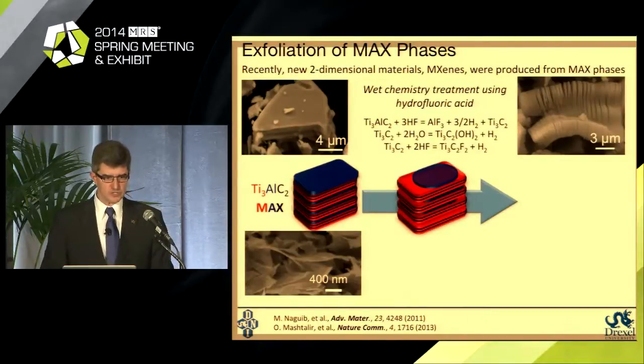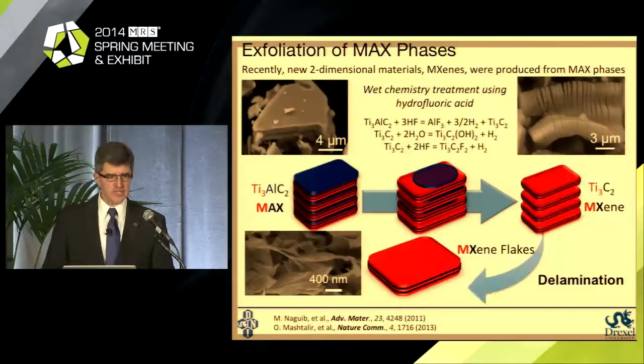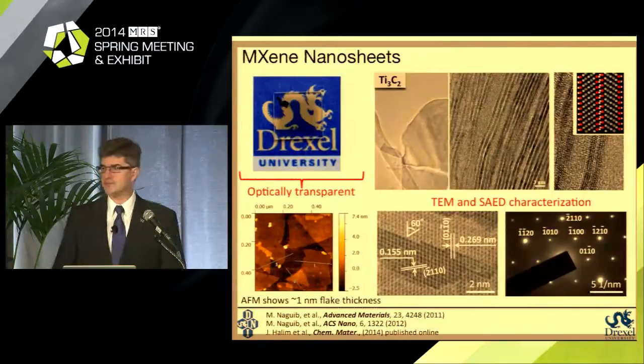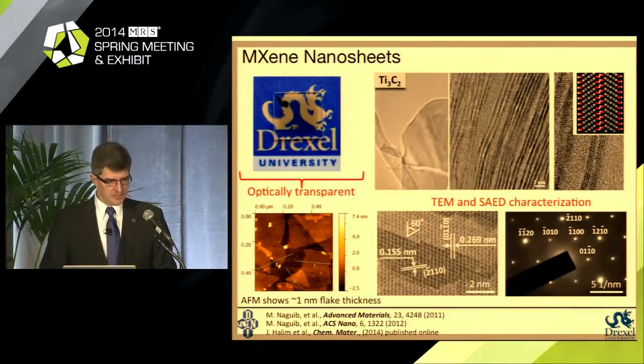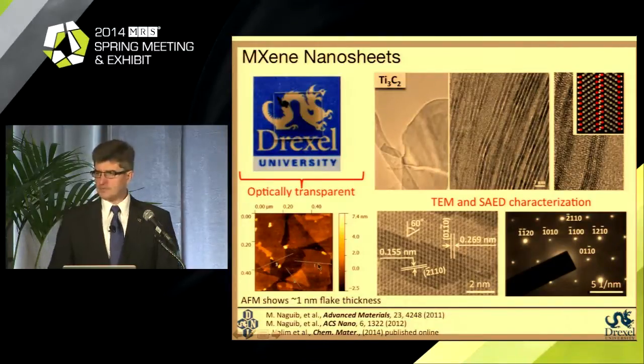And if you do this etching, you will end up with this structure, which looks very much like exfoliated graphite, which is used in battery electrodes and may look familiar to people who work on graphite. And if you sonicate it, you can get single flakes of this material. This material behaves in all aspects just like other two-dimensional atomic crystals. They are transparent in nanometer-thin films. If you do atomic force microscopy, you will see that those 1 nanometer flakes correspond to a single layer